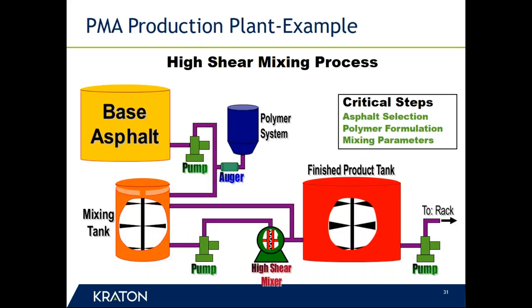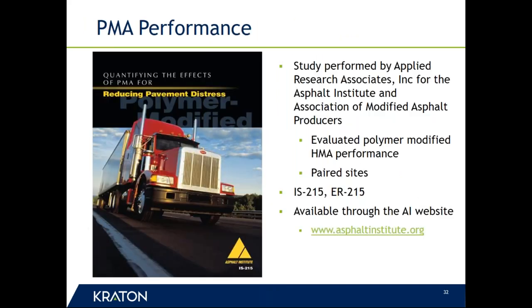Not going to spend a whole lot of time here, but just the process of making SBS. You saw a glimpse of what you do in the laboratory. This is blowing it up to industrial scale, where you would have a high shear mill involved, which will help break the polymer particles down to smaller ones that can be more rapidly incorporated into the asphalt binder or can absorb portions of that asphalt binder more quickly and more thoroughly, and then opportunity to store during blending to where you get the time and temperature effect, and then off to the rack to where it can be delivered to projects.